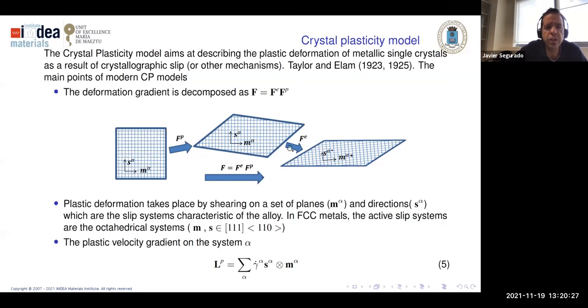The first thing is that we consider two configurations. So this is the material with the lattice, you see it here, and we consider that for deforming the material, we have two types of deformation. One is called the plastic deformation, that is this configuration, where we only consider the deformation due to a slip. So there are some direction, S, and some plane, M, in which we have a shear from one part of the crystal to the other, and this is represented here. So we have a change of shape, but we don't have volumetric deformation, and the lattice, that is more important, has not changed. That is why we keep this square.